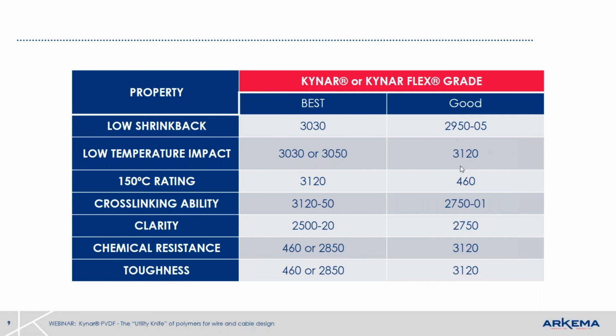But this other heterogeneous grade, 3120, is very good, but not as good as the 3030. 150-degree rating, we have a variety of materials, homopolymer and copolymer. PVDF is able to be cross-linked. Cross-linking increases the service temperature of the material. So these grades here, 3120 to 2750, are common Kynar grades for cross-linking.